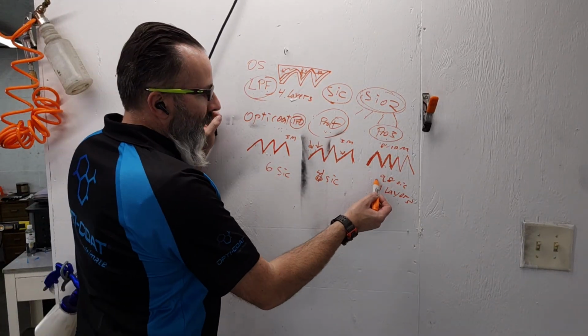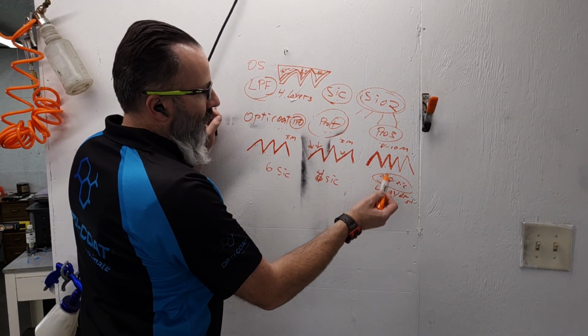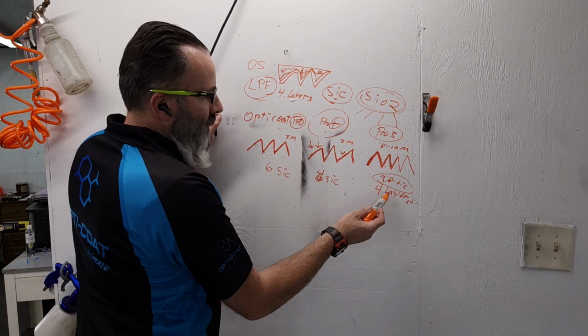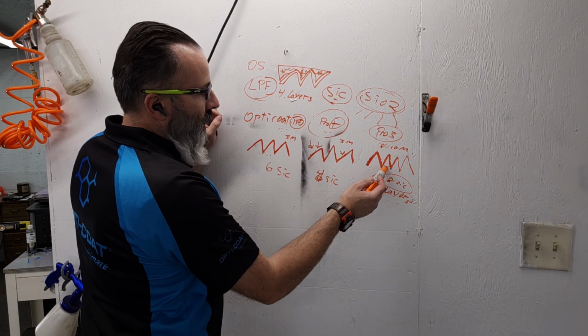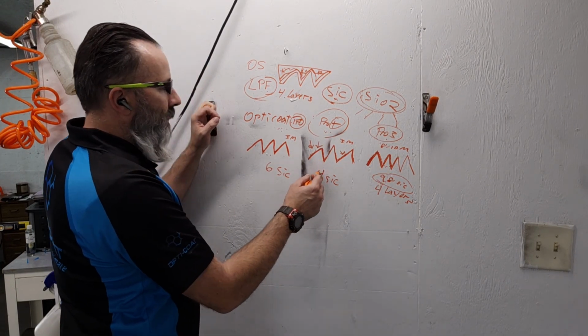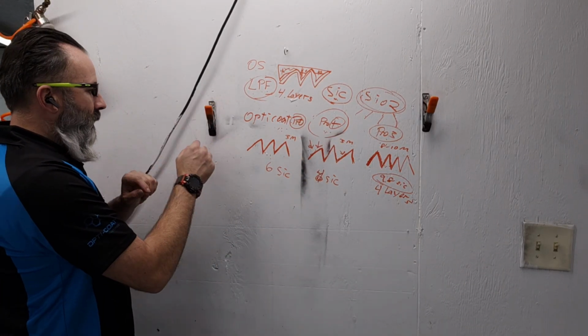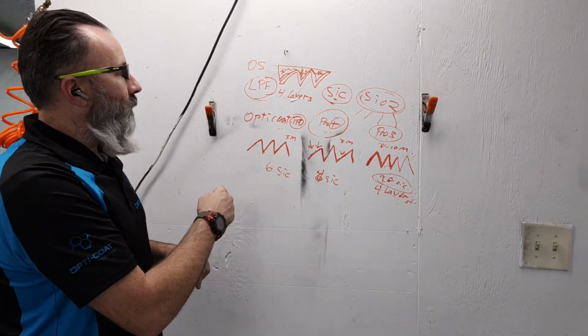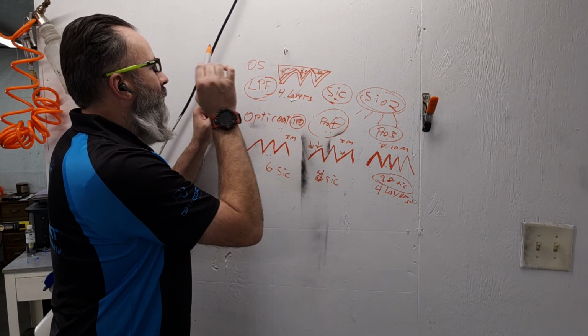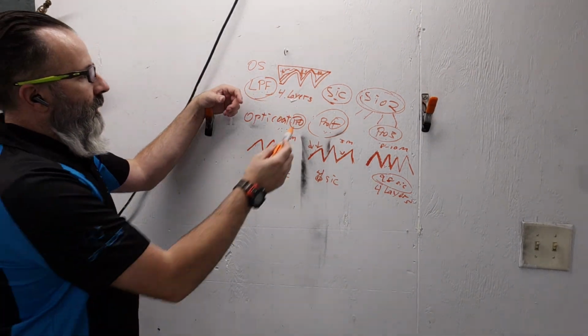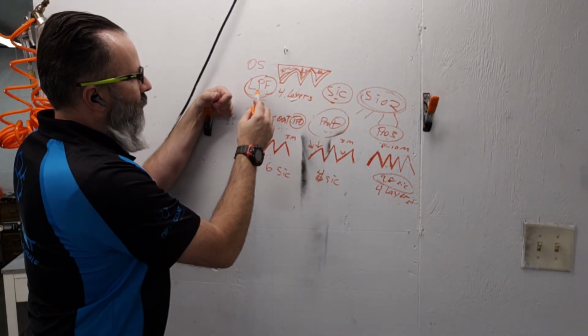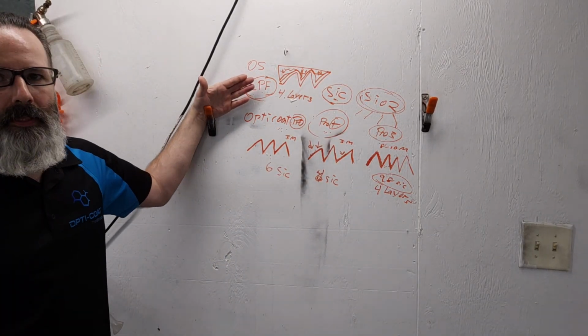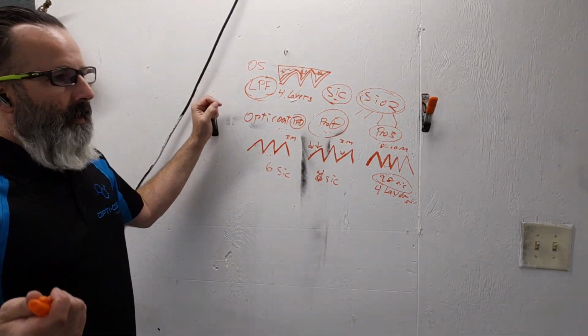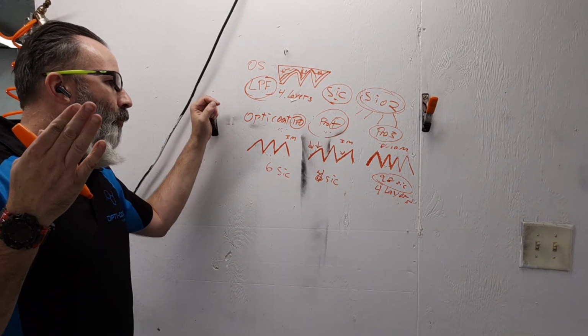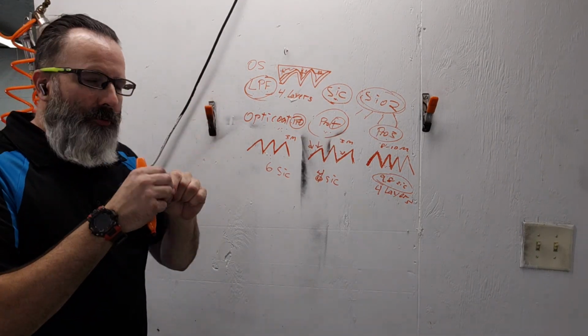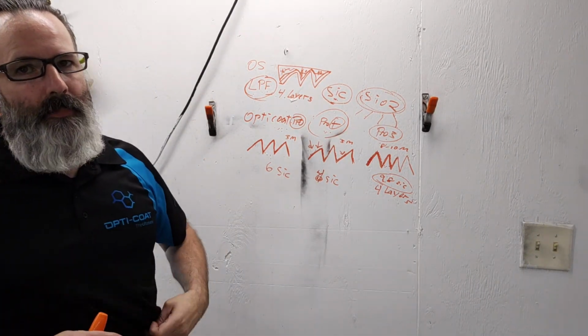And why is that? It has even more silicon carbide than the Pro 3, which also has more silicon carbide than Pro Plus and Pro, and then Ultrashine, which is not here on the wall. But that's why Opti-Shield is in a different category. It's kind of a new category. So this LPF replaces the traditional, if you're familiar with paint protection film, which is an extruded film. Now it's extremely thick. It's 8 mil thick, but it has to be.